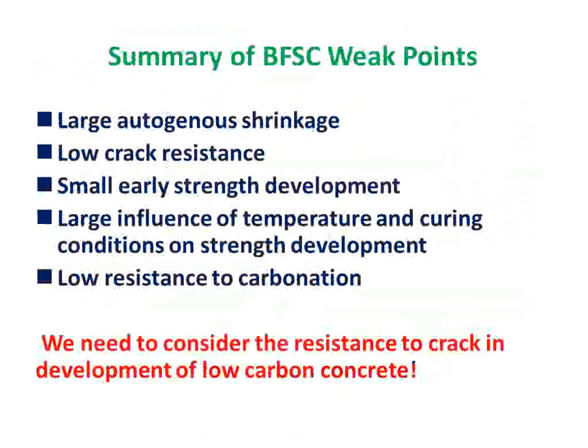So if you summarize the blast furnace slag concrete weak points, one is the large autogenous shrinkage, low crack resistance, smaller strength development, large influence of temperature and curing condition on strength development, and low resistance to carbonation. You can reduce carbon dioxide emission drastically by utilizing this kind of concrete, but we have the weak points as written here. As a result, we can say that we need to consider the resistance to cracking in the development of concrete.